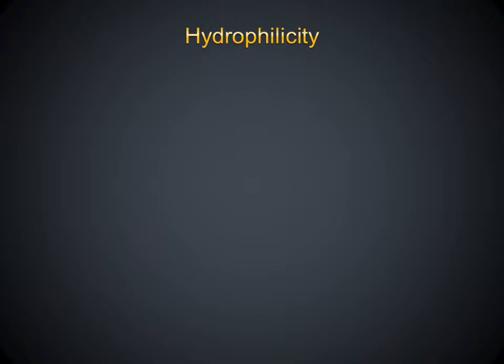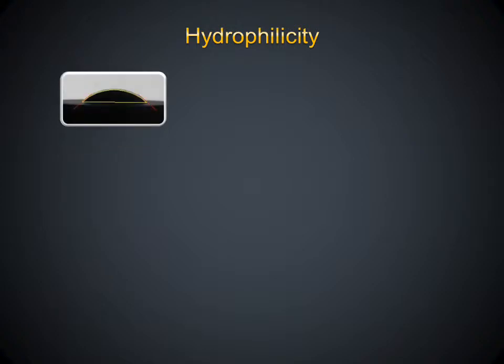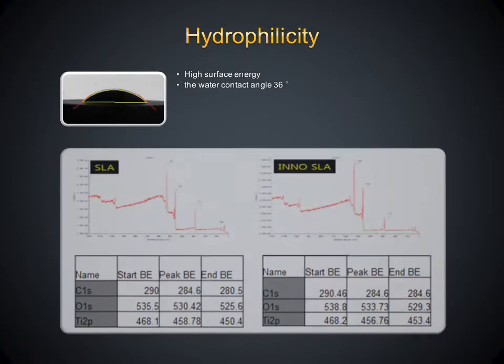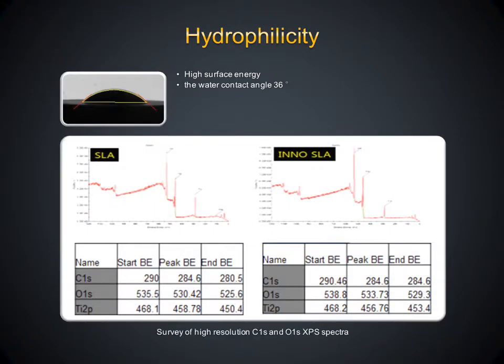After alkali solution cleaning, the oxygen element surface energy is increased to a high energy status, 533.73 eV from 530.42 eV. In static water contact angle measurement, the water contact angle is decreased from 133 degrees to 36 degrees, which means hydrophilic according to the below 45 degrees hydrophilic criteria.